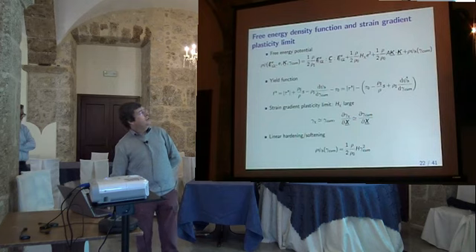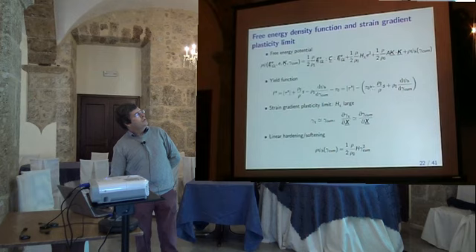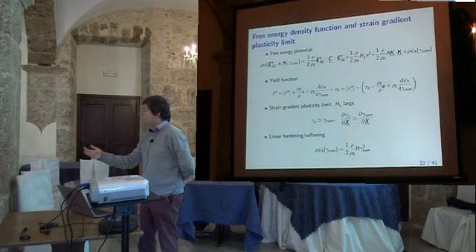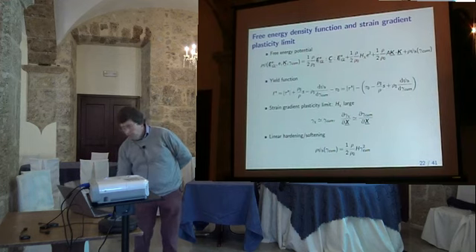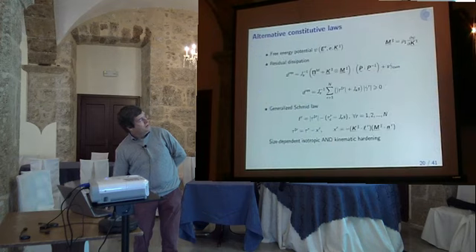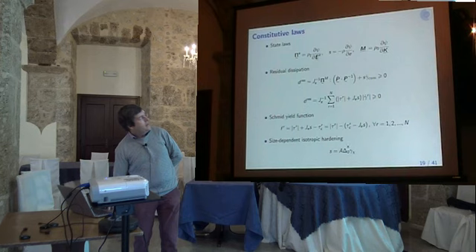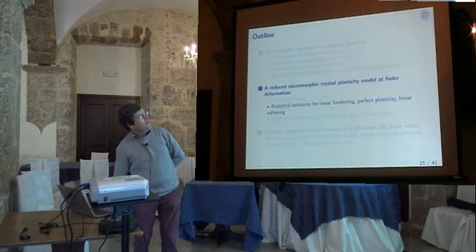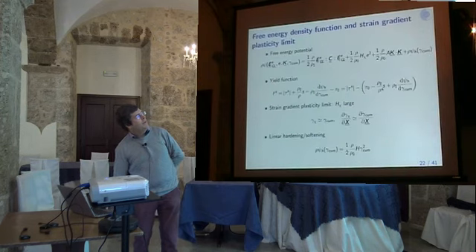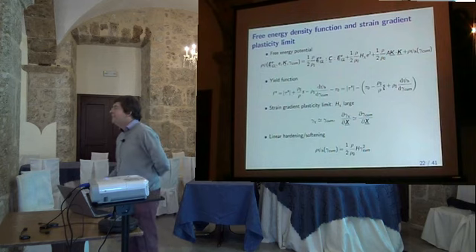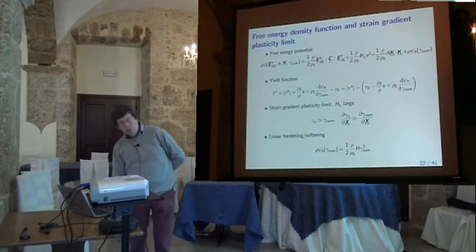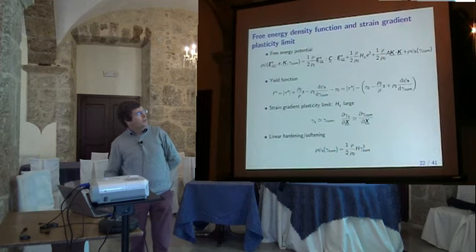And so we see now that this is the yield function. So you see the initial yield stress here. You see this hardening due to the microstress tensor, which is there. And this is in fact the effect. Remember that in fact this S, oh sorry, it was there, I think. Yes, it was there. You have a Laplace term in fact. So this is the usual Laplace term here that you know from Aifantis, for instance, okay? And you have, of course, standard hardening, which comes in addition to that.